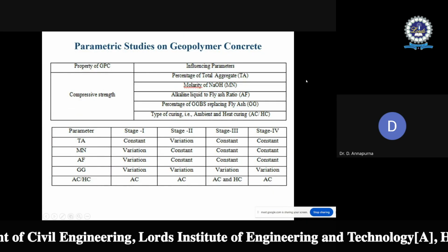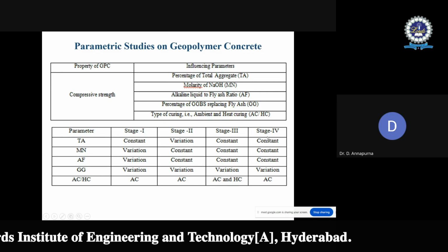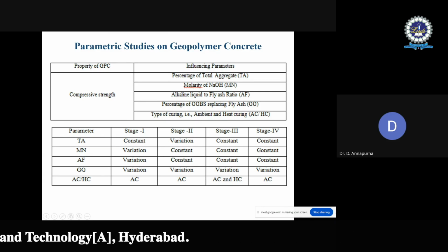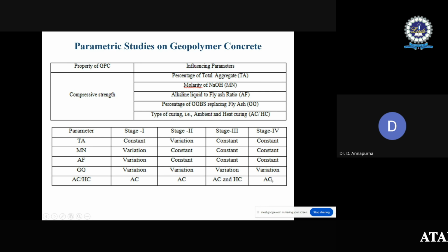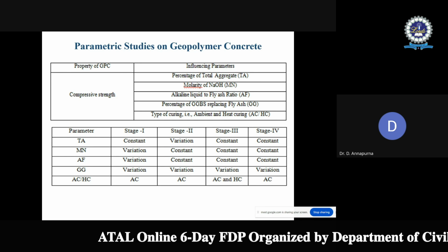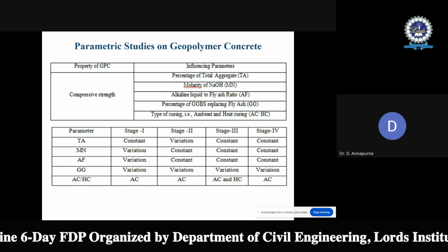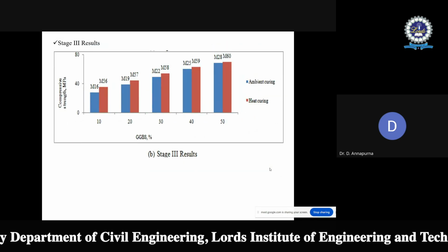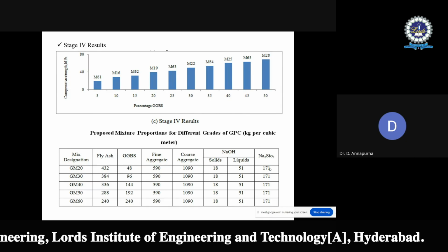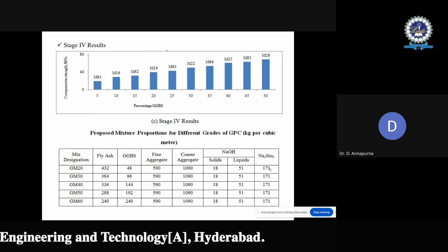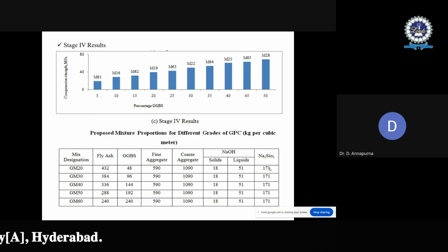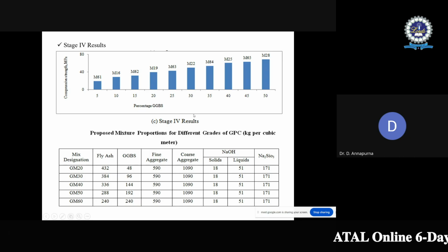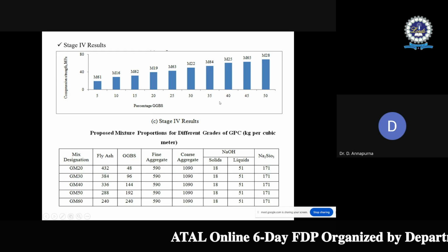So in the fourth stage, we have total aggregate content as 70%, molarity 8, and alkaline liquid to fly ash ratio as 0.5. Then ambient curing conditions are considered, and then the variation of GGBS, because it is seen that from 10 to 50% it has shown a good improvement in the compressive strength. That is the reason now only the GGBS dosage, how it is going to improve the compressive strength, is studied by decreasing the interval to 5%, that is 5%, 10%, 15, 20, 25 like that.